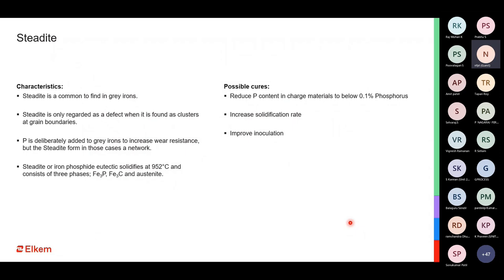When you have a higher phosphorus percentage, these steadite phosphide eutectics try to accumulate near the grain boundaries and give you poor machinability. In some cases of gray iron, where you need wear resistance, some foundries do add phosphorus to get the steadites. But then it is very important that you have steadites present as a network throughout the casting and not segregated to one or a few locations where they can form iron phosphide eutectic.